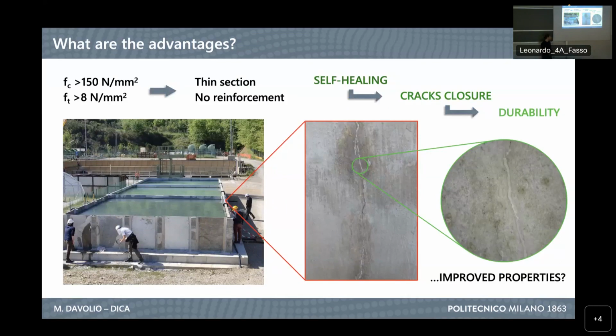And from the durability point of view, you can see here a real-life application, and the self-healing capacity of the material closes the cracks that happen in concrete, as we know, and thus fosters the durability of the structure itself, limiting the penetration of aggressive agents inside the matrix, and thus the corrosion of the reinforcement.